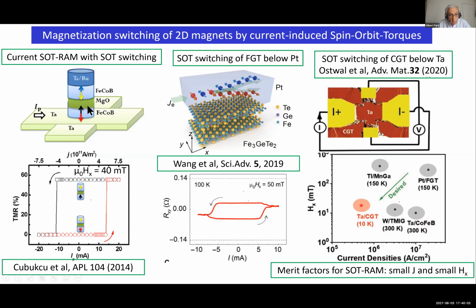And so the two states of the memory correspond to the parallel or anti-parallel orientation of the magnetization in the two magnetic electrodes. And in a SOT RAM, the switching of the state of the memory is obtained by a current in the tantalum layer, using the spin Hall effect in the tantalum layer to inject vertically a spin current into this bottom layer, iron cobalt boron, and to reverse this magnetization.